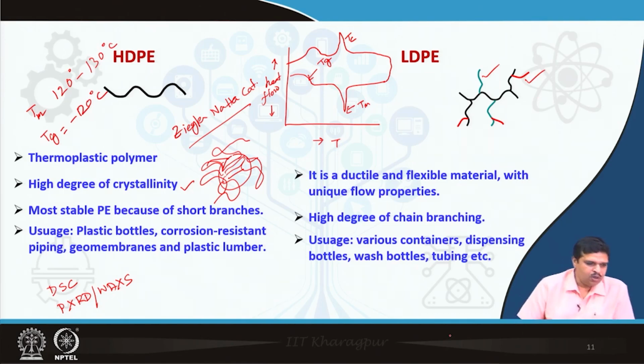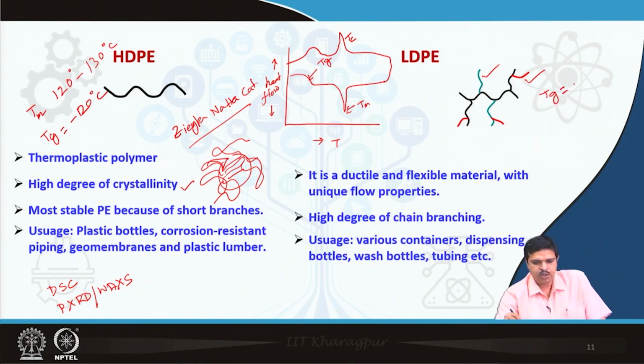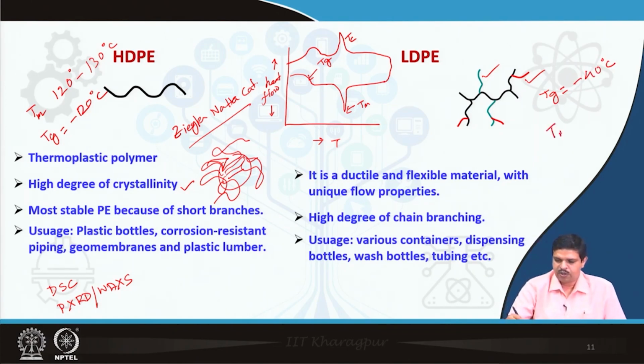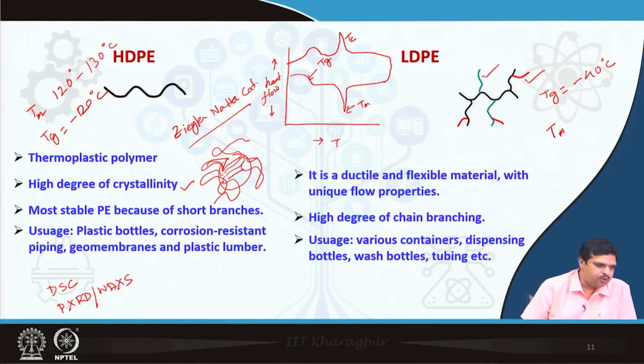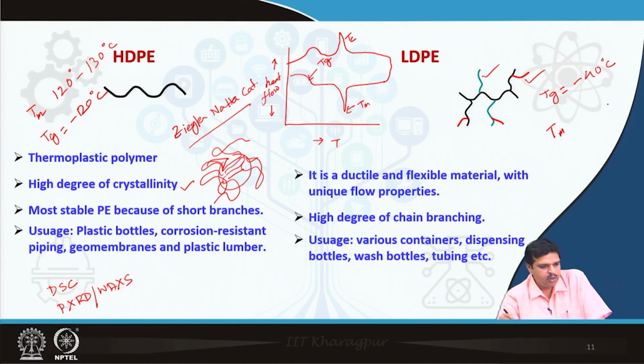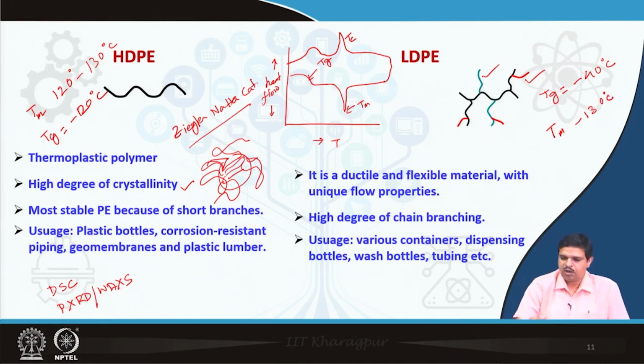And here you will see that these polymers will be quite soft, because the Tg is around minus 40 degree centigrade. And Tm, the melting point temperature, in many cases may not be visible. But if the side chain is less, then you can get the melting point temperature at around minus 13 degree centigrade, something like that. But again, I am telling you that it depends on the number of branching and the length of the branching.